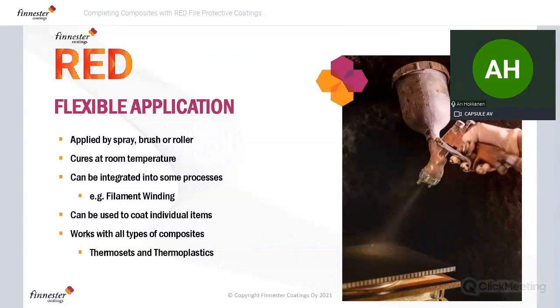As I mentioned earlier, we prefer recommending a spray application, but you can also apply our technology with a brush or roller as well. Another benefit is that this technology will cure at room temperature. So obviously, if you have big pieces, if you're manufacturing composite bridges in one piece, for example, or large panels that don't fit into ovens, then this technology is ideal for that application because you can just leave it and allow it to cure at room temperature.